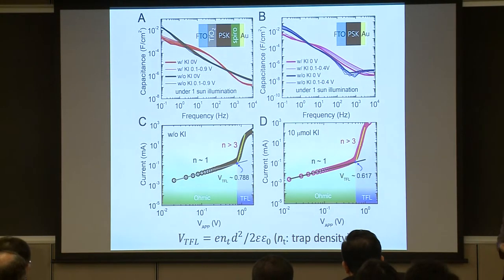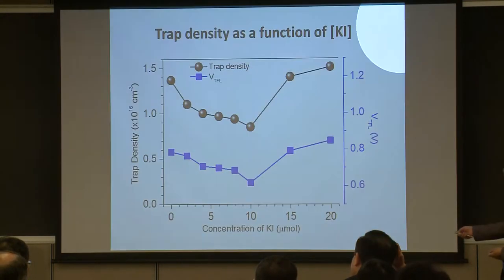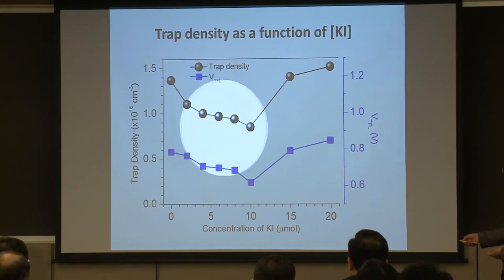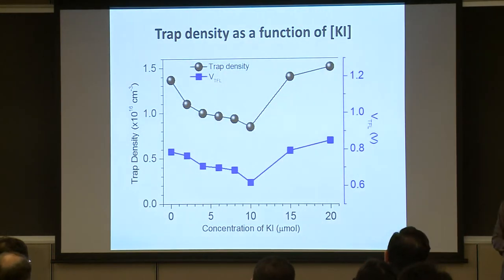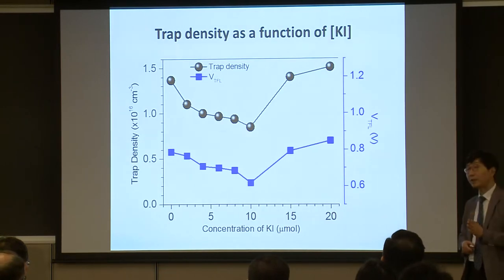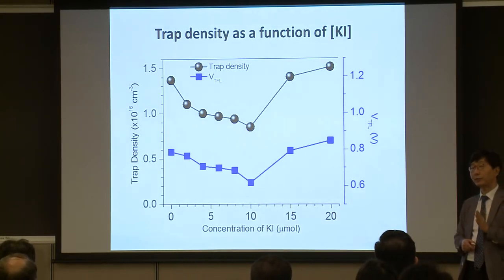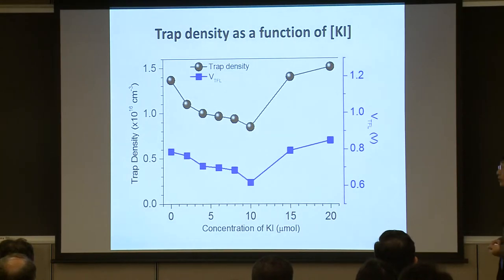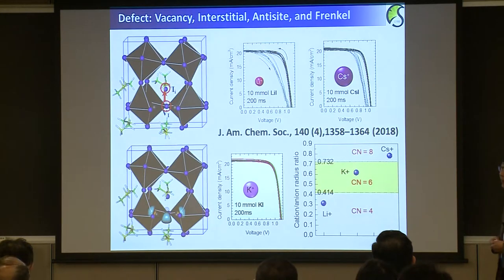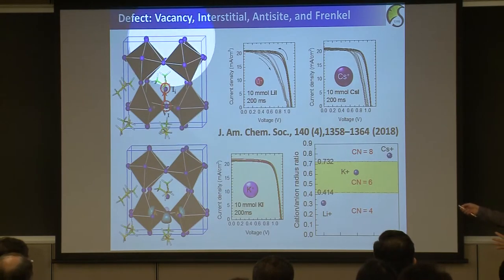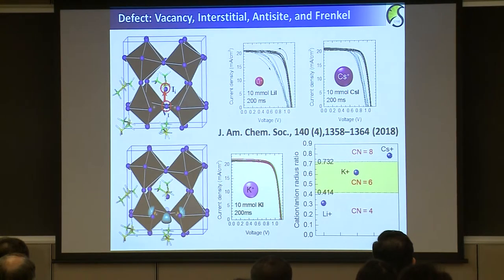And then also from the SCLC measurement, we found that the trap density slightly decreases, which is related to the IV hysteresis. So probably the decrease of defects by the addition of potassium iodide may be related to the removal of IV hysteresis. So we calculated this computationally, and among the many defect structures, for instance, vacancy, interstitial, antisite, Frenkel defect, we have some reasonable data from the Frenkel defect analysis.